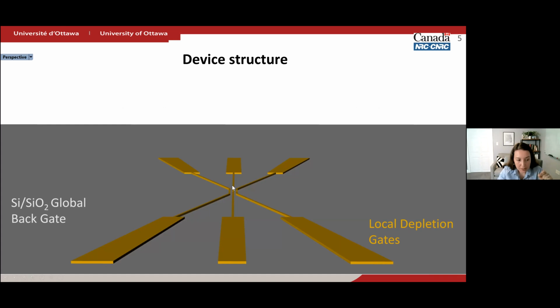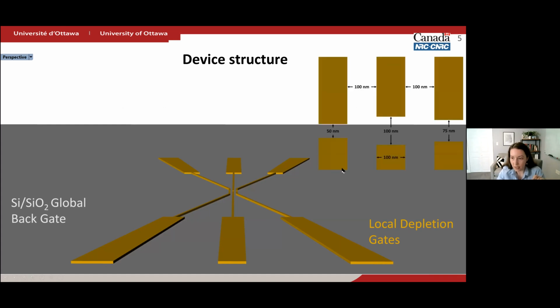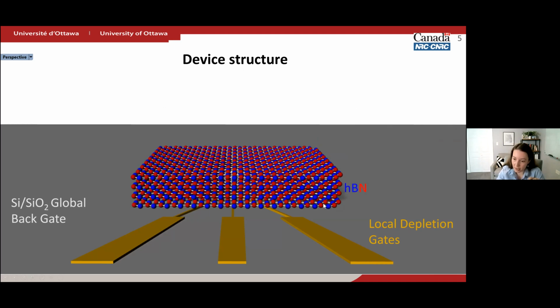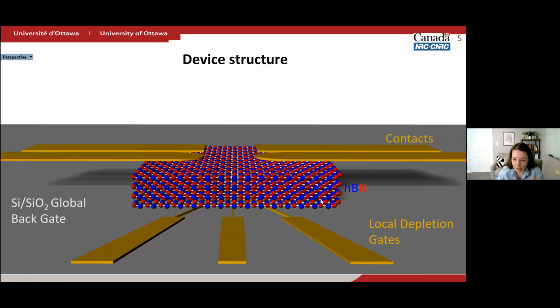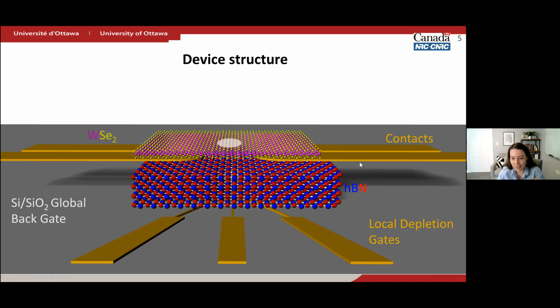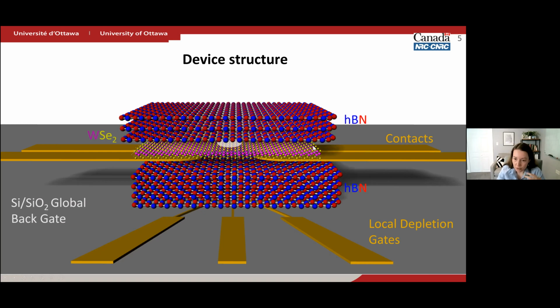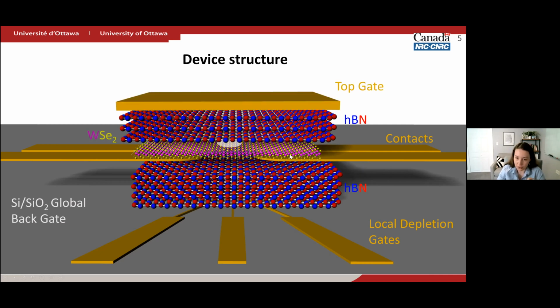And so basically, we try and have some local gates. We then, with different widths, place hexagonal boron nitride as a gate dielectric, 20 nanometers in height, a few microns in width. We place metallic contacts on the gate dielectric. We place a semiconducting atomically thin layer, in this case, tungsten selenide. We aim to create a quantum dot over there in the center. We encapsulate this with hexagonal boron nitride, both for protection, but also as a top gate dielectric to further control the charge carriers. Actually, that turns out to be a useful knob for tuning the contact resistance.